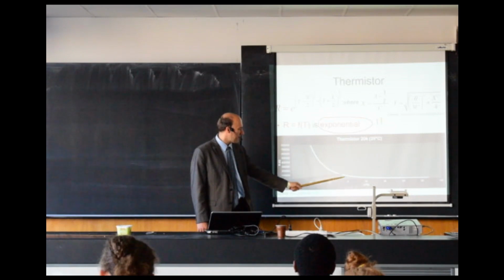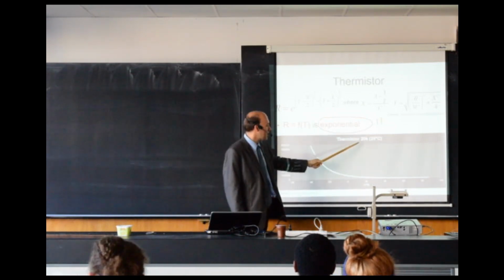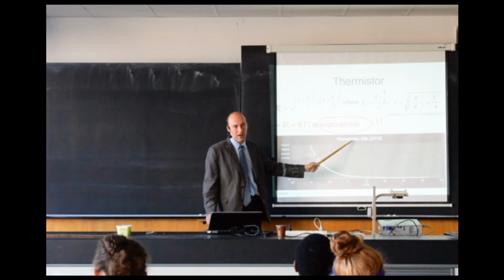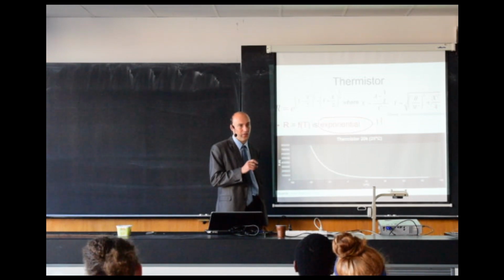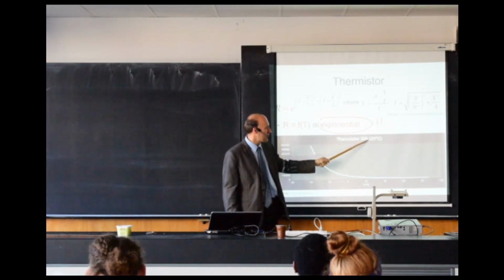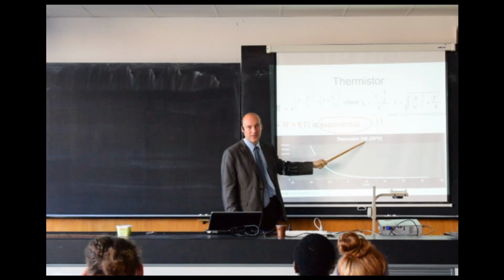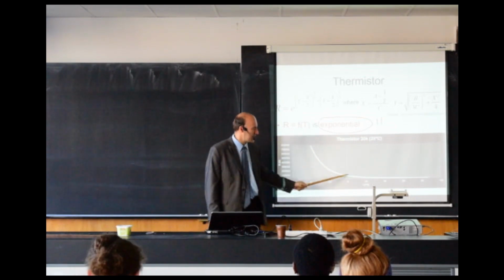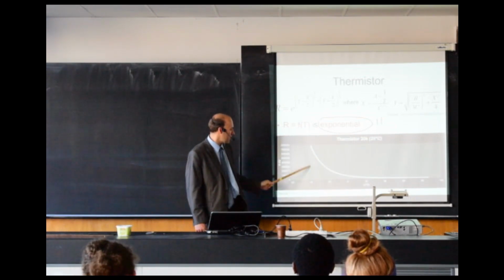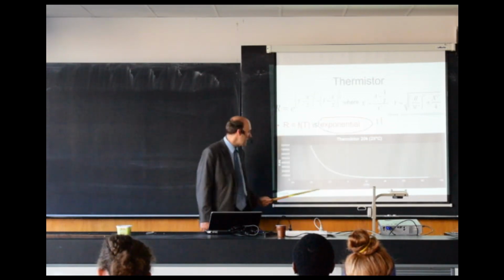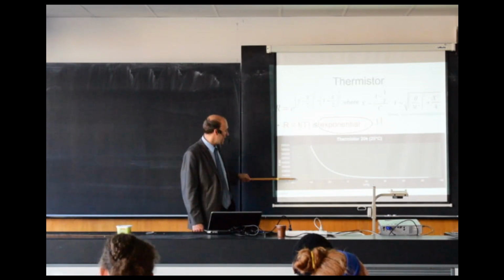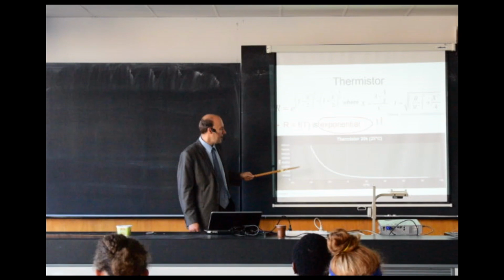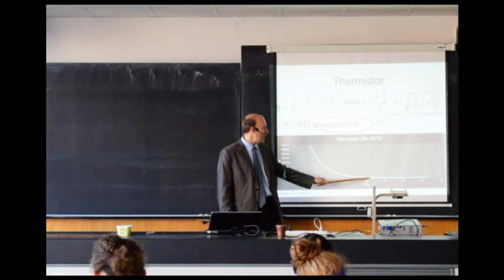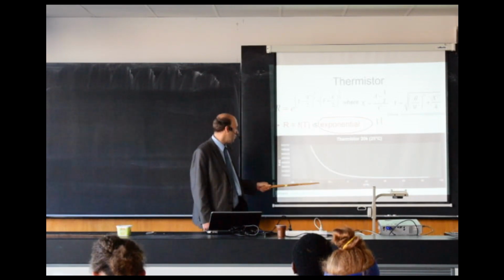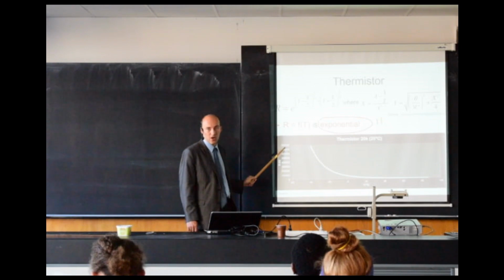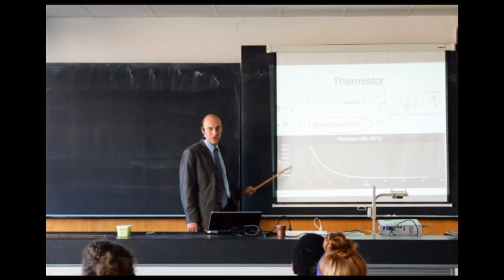Here you have the curve plotted for a thermistor that has 20 kiloohms at 25 centigrade. For RTDs, we had the number valid for 0 centigrade. For thermistors, it's typical that you will see the value for 25 centigrade. And here is the exponential dependence. Here is temperature from roughly minus 40 to 80 centigrade. And you see the electrical resistance is changing by many orders of magnitude. The 25 centigrade are somewhere around here, and here we have 20 kiloohms. If I would go to, let's say, minus 40, I would have 800 kiloohms. So there is a really large change of electrical resistance.